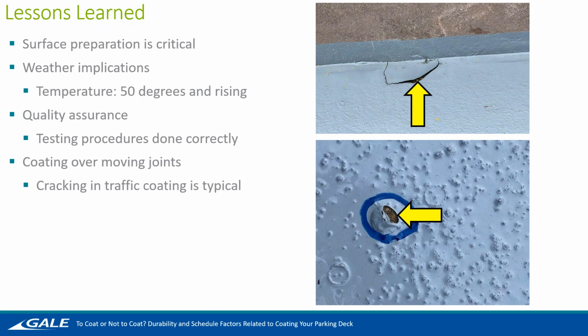So we found that if you install at the peak temperature, roughly around noon, and you install into the afternoon when it's starting to slowly cool off, it turns out to be a lot better of a product, and there's a lot less defects that come up to the surface. We've also noticed that if you're coating the top deck of a parking garage and there are buildings around you shading the sun in the morning compared to the afternoon, it could also vary the cure times. The sun is beating down on it, heating up the concrete in one area compared to the other area you're coating. So there could be isolated defects in one area where the sun's not completely beating down.